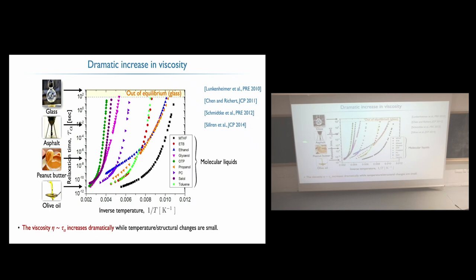At some point, you hit something like asphalt. So Misaki, you say it's one drop in 10 years. So you have this material, and it makes one drop every 10 years, so very different from the olive oil. And then at the glass transition, well, you have the glassy material. So really, when we say that it's dramatic, it's really dramatic. It's really the same material, you change a bit the temperature, and it goes through all these states.